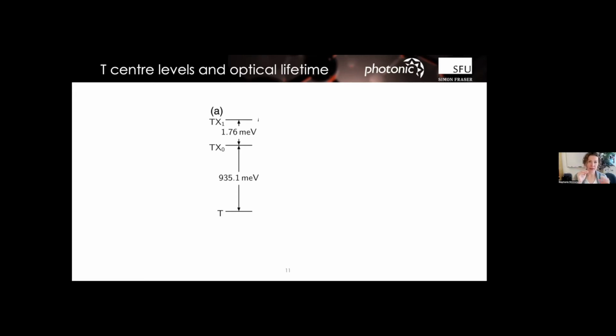And that is an exciton. So you're adding an exciton to the system, and an exciton is an electron-hole pair. And so the electrons form a singlet, so they have no more magnetic contributions, but you also have this unpaired hole now in the excited state. So the excited state here has a hole in silicon comes from the valence band.